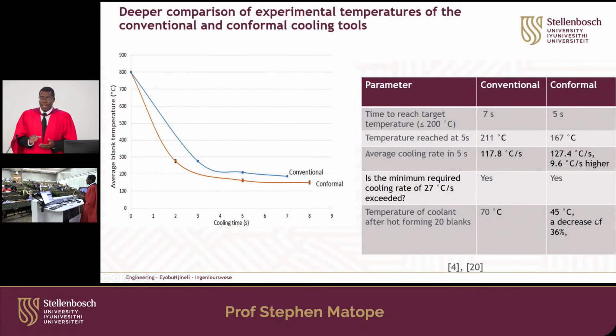We found that after pressing about 20 blanks, our conformal cooling stagnated at 45 degrees Celsius. That means you can even produce more, but still have the 45 degrees maintained. But for the conventional, the temperature was 70 degrees Celsius, which is quite high, which means there will be more thermal shocks on this tool. On the conformal, it is better, which means less heat, less thermal stress, and better performance of our tool,